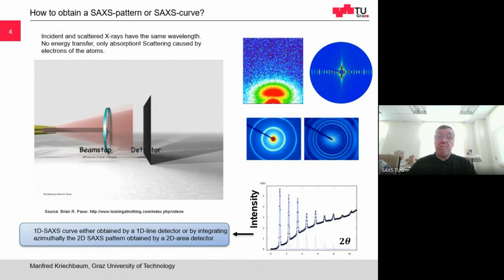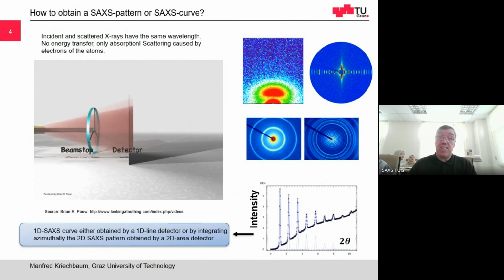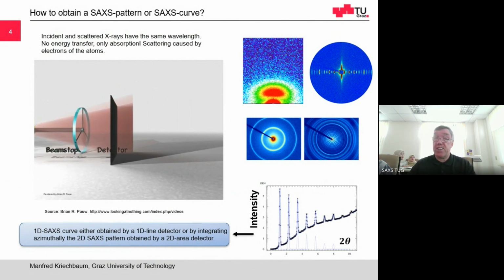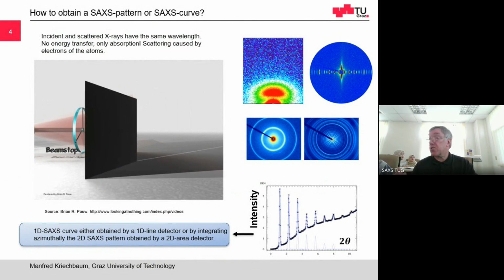One thing you also have to remember, the incident and the scattered X-ray beam have the same energy. So it's not spectroscopy where some energy transfer occurs. It's elastic scattering without any energy transfer. And the scattering is caused by the electrons in the sample or in the molecule. So if you have a sample with a homogeneous electron density, you almost get no scattering. You have a flat baseline.